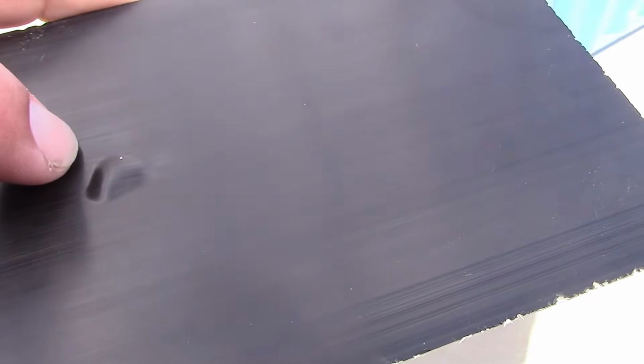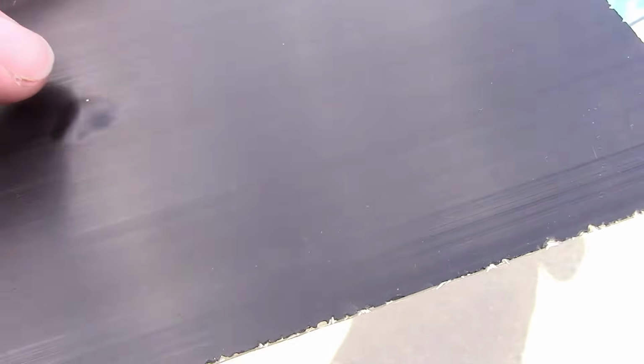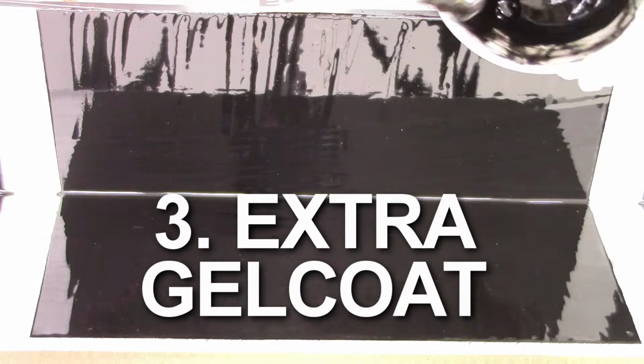Most panels look fine when demoulded using this method, but the issues tend to appear later. This corner will easily break away if the panel receives any impact. Also, when exposed to outdoor environments, especially warm temperatures, it will blister as the air or styrene gases between the layers start to expand in the heat. Here we've demonstrated this effect on a test panel left out in the sun.